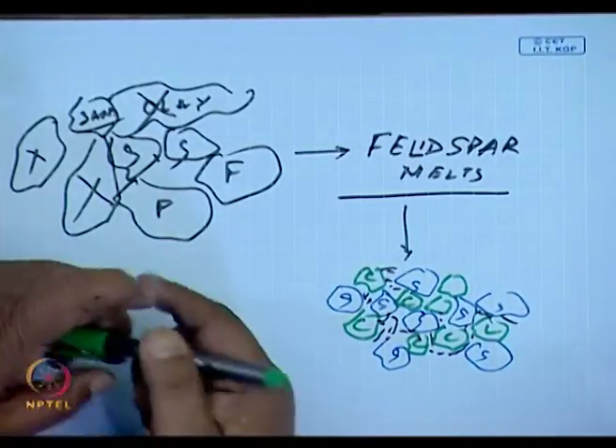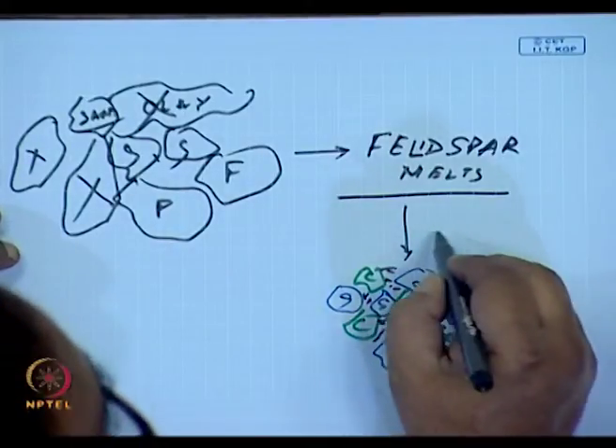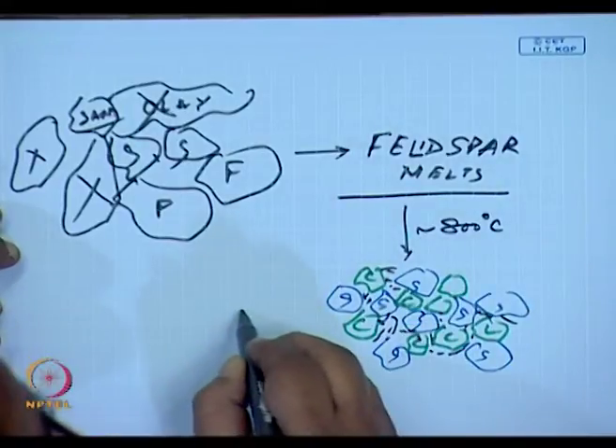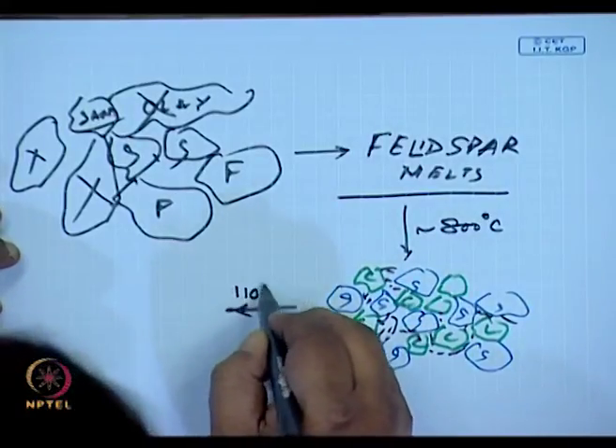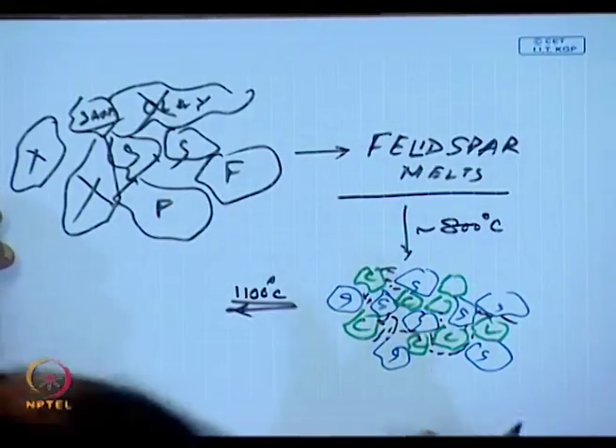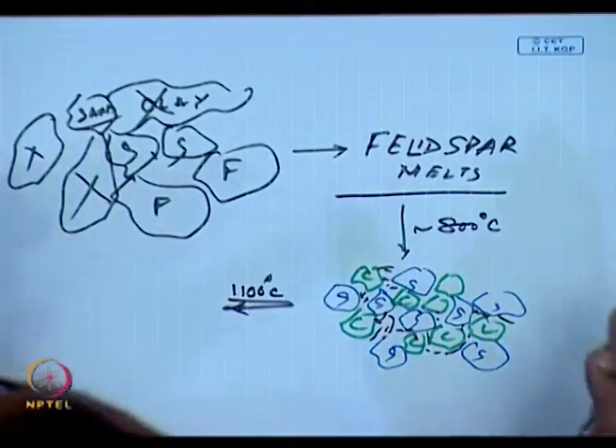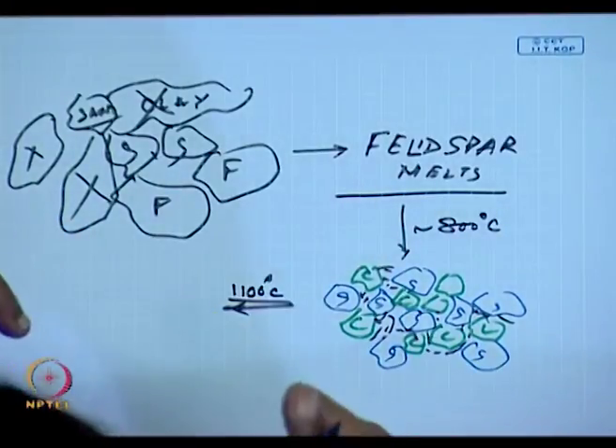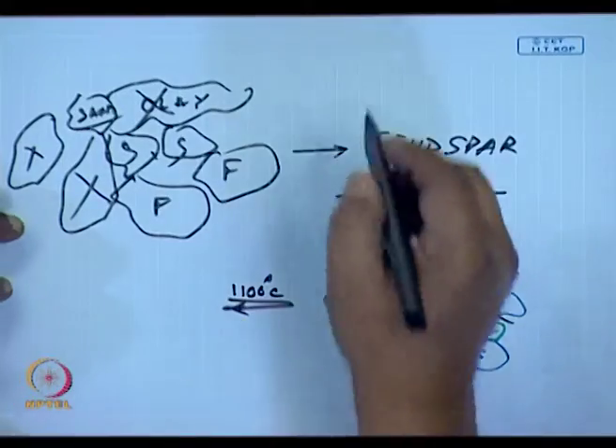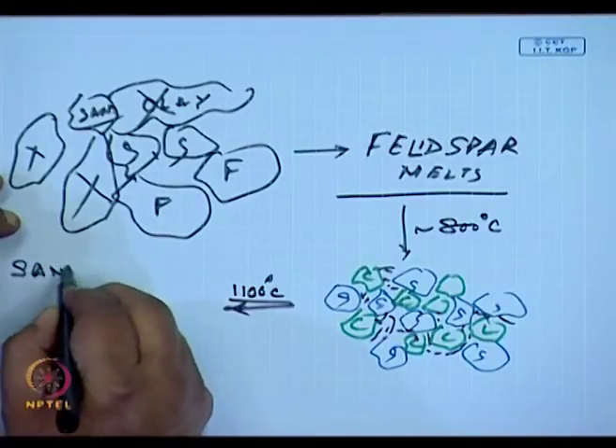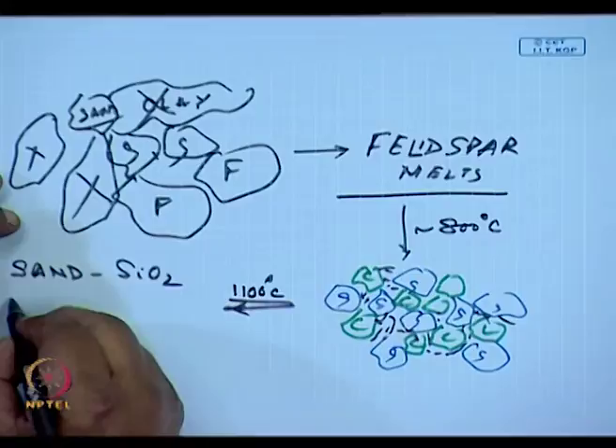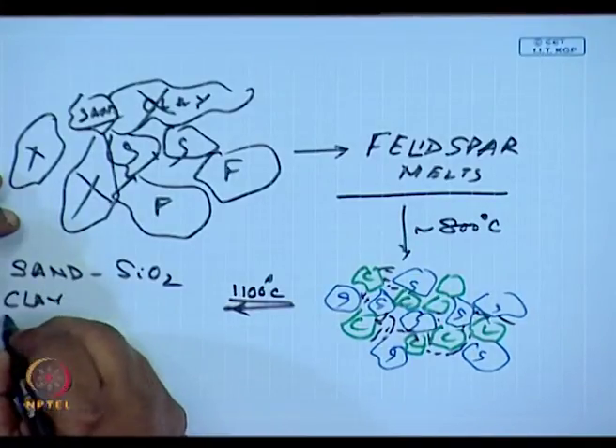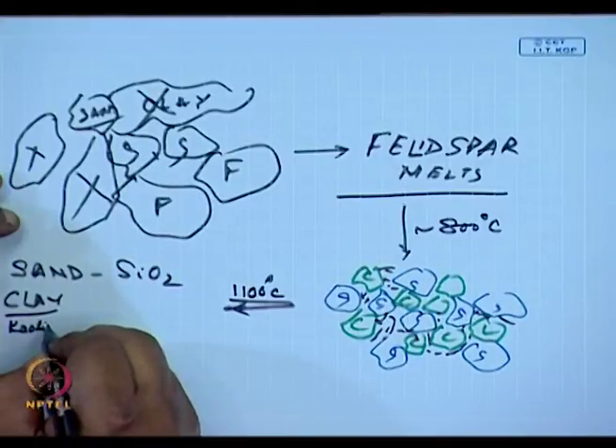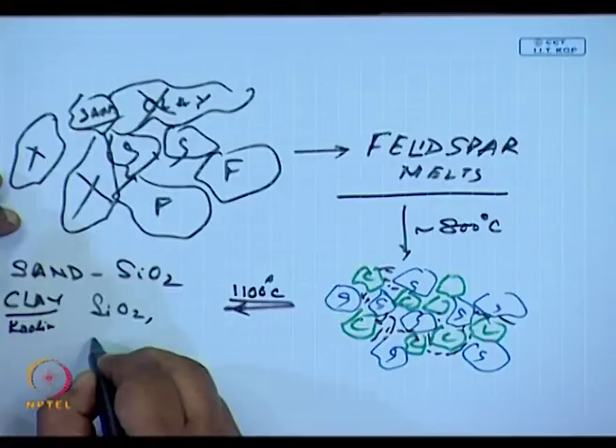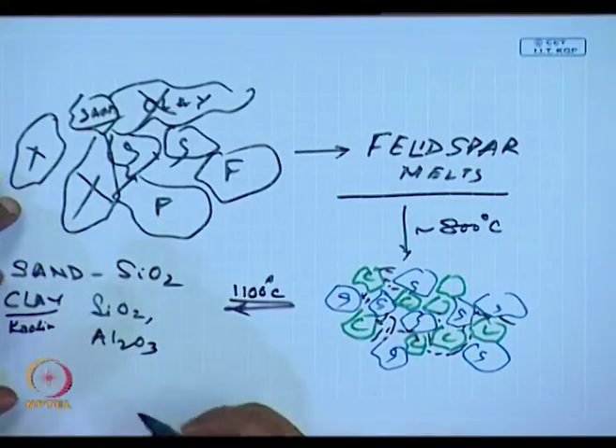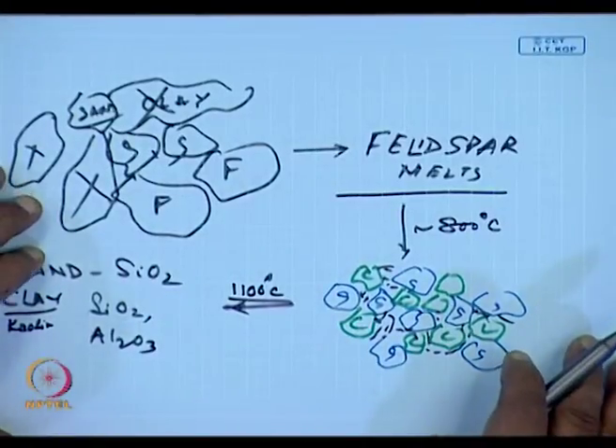As this material is heated past, let us say I said 800 degrees centigrade or so, as it is heated past 1100 degrees centigrade, you will see later that the kaolin decomposes to give you silica and the rest of the materials. But let me focus on one thing: sand is pure silica. Clay, which includes kaolin, is a mixture of silica, alumina. So these are called basically aluminosilicates. That's what the word keramos came from.